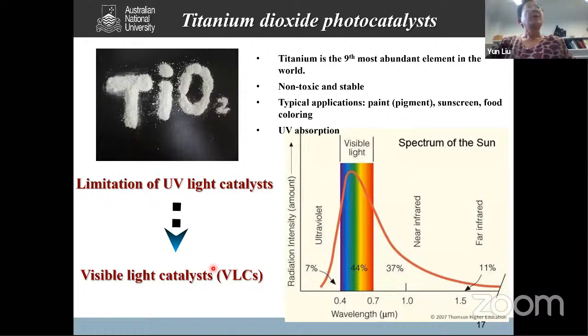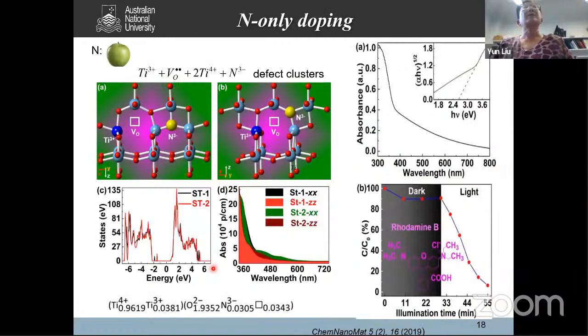Okay, but unfortunately, it's not very successful. One of the things to move into visible light is, for example, typically you use nitrogen to replace oxygen to raise the valence band. In that case, you can narrow the band gap. But nitrogen, in comparison with oxygen, is quite different. You assume nitrogen is 3 minus, so I would use 2 nitrogen to replace 3 oxygen sites and generate 1 oxygen vacancy. But because the electronegativity is different, that makes the defect cluster more complicated.